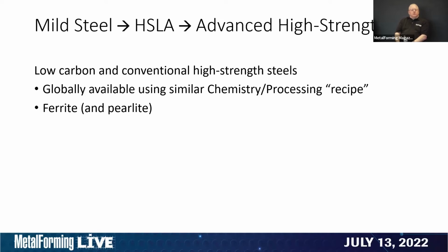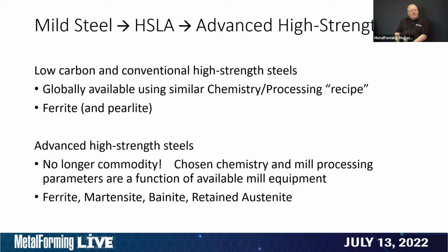The biggest difference with advanced high strength steels is that the steel makers are constrained by the equipment that they have. There are specifications for advanced high strength steels that have fairly large windows of yield strength, tensile strength, elongation, n value, the important properties for forming and formability. But the windows are pretty large, and that lets the steel maker optimize their mill processing and their chemistry to their equipment to achieve those property ranges.